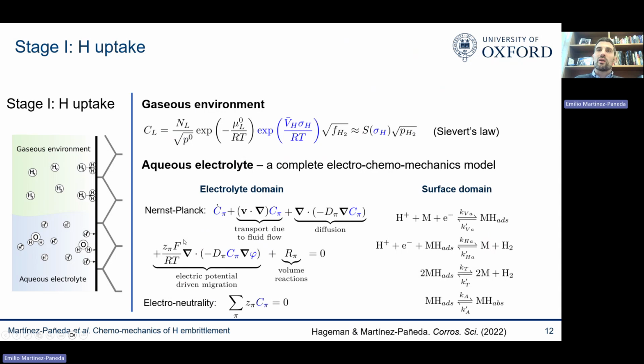The good news is that we know the differential equations that describe each of these phenomena. At the surface, we have the Volmer, Heyrovsky, Tafel, and absorption reactions, so you need to resolve those hydrogen evolution and absorption reactions—again, we know the maths for that. And in the electrolyte, you solve for the electrochemistry using Nernst-Planck and the electroneutrality condition, which are relatively well established—the type of models and equations that we like.